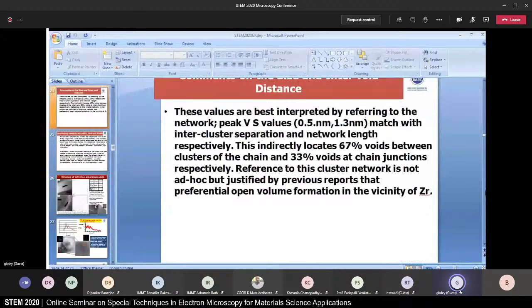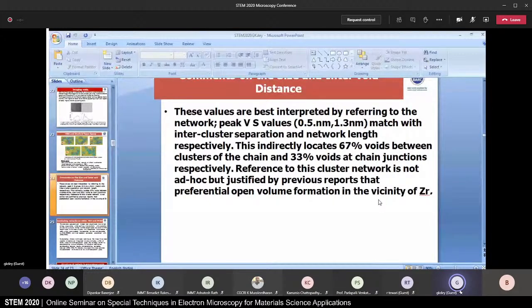The void sizes are shown here, and this is the peak of the void size, and this is the inter-void distance. And these could be correlated to the structure of the glass in a very nice way, and that is what is summarized here. The voids are present at the end of the clusters, that is the medium range order domains. This is the first time we are showing that the voids are present at the end of the medium range order domains.